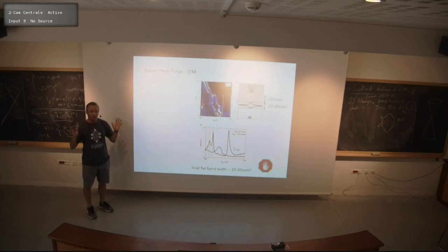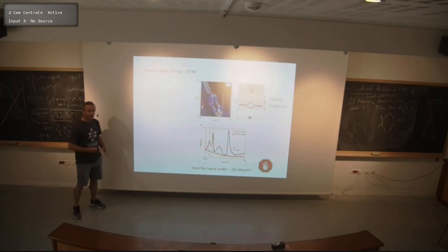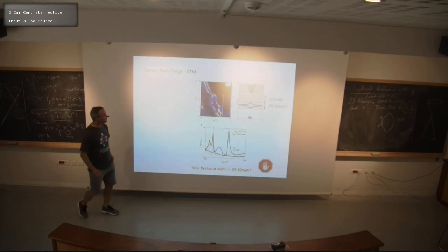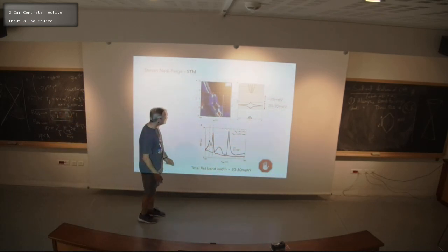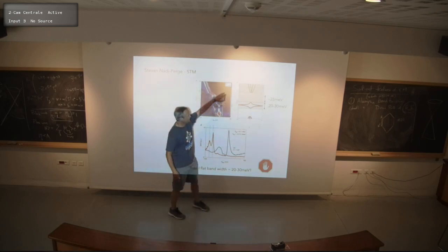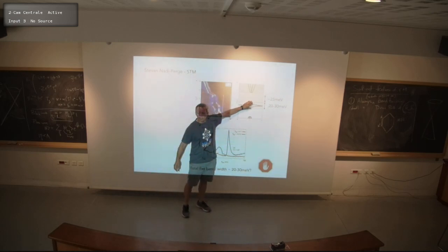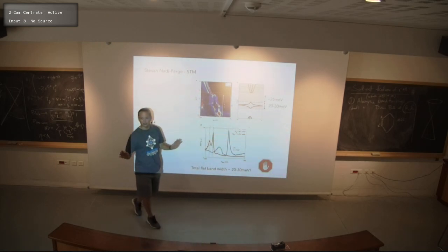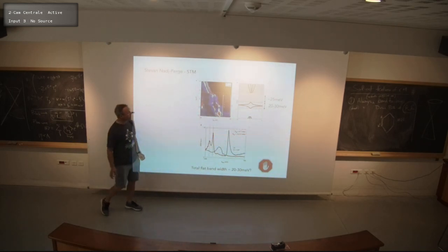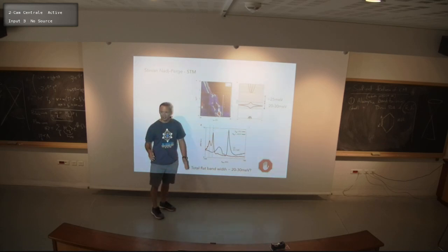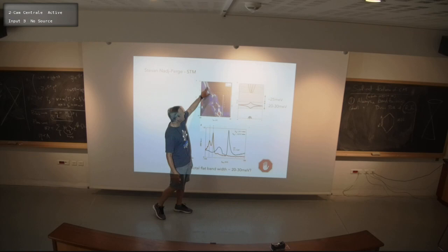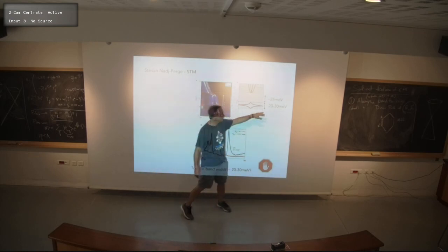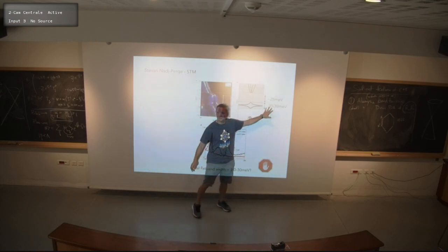It's some complicated many-body object, the one-particle Green's function, which, for example, DMFT likes to calculate, okay? Up here, with the Fermi level up here, these bands are now very far from the Fermi energy. They're just fully occupied. So they are not correlated at all anymore, and we can just measure the actual energy it takes to extract an electron from one to the other. And the difference is the best measure we can get of the width of the bands, and it's something like 20 to 30 millivolts, okay?